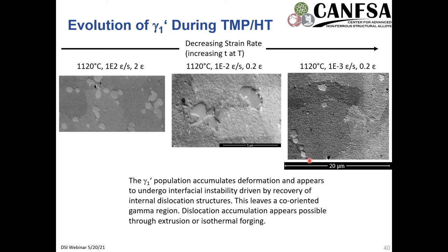And this is believed to be because we're disrupting the interface of the primary gamma prime enough that we're kind of obliterating it in some sense. This is really driven by what we believe to be the dislocation structure within the primary gamma prime. You can also have gamma boundary movement through the primary gamma prime through a discontinuous reprecipitation mechanism that we're currently exploring. And here's an IPF, or inverse pole figure, map overlay over the region, showing this is all with the same orientation. And this one as well here.